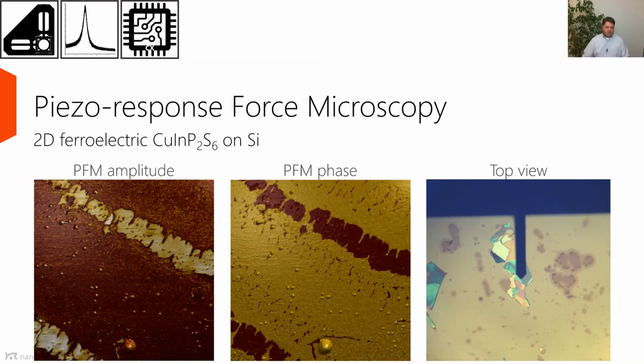Then we also have another electrical mode, which is the piezo response force microscopy. What you see here is this 2D ferroelectric material adsorbed to silicon. And what you can see here nicely is the amplitude of the piezo response of this material, and also the phase change of these materials, depending on which material you're on. So it forms these islands, it has these structures. So it's basically a thin film on silicon. And yeah, we could get a quite nice contrast here. So this is almost 180 degrees phase change between the different phases or parts of this sample, which is what one would expect to some extent.